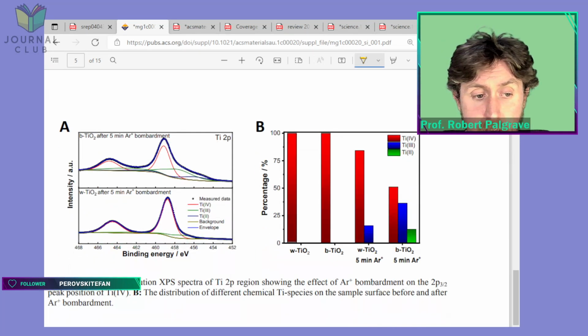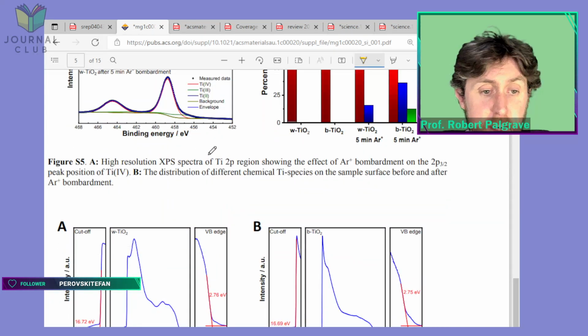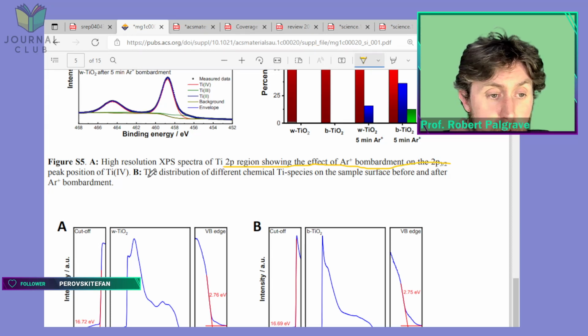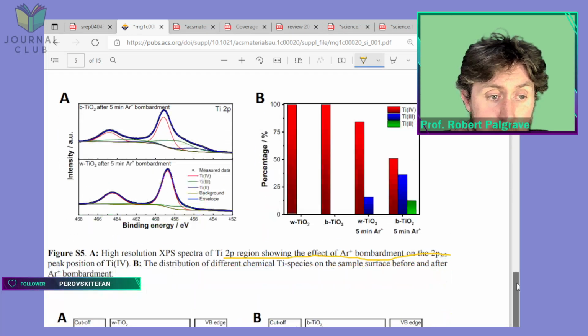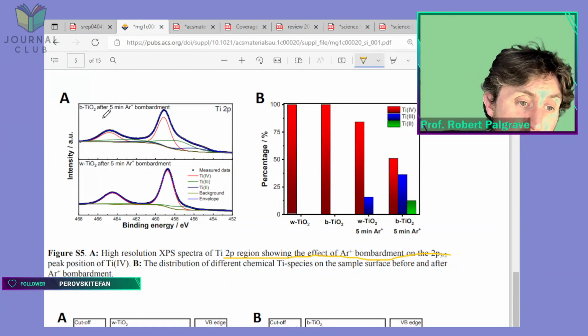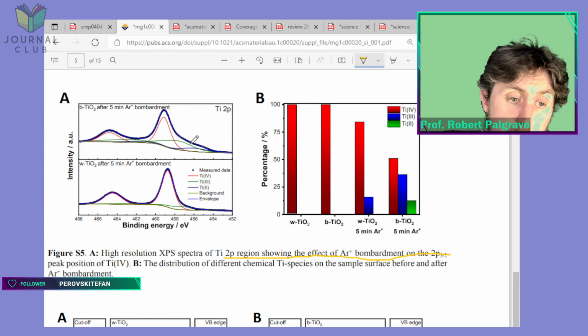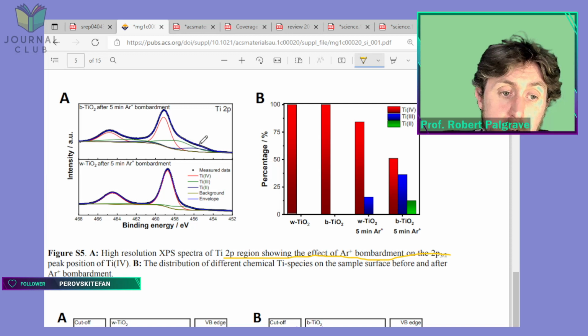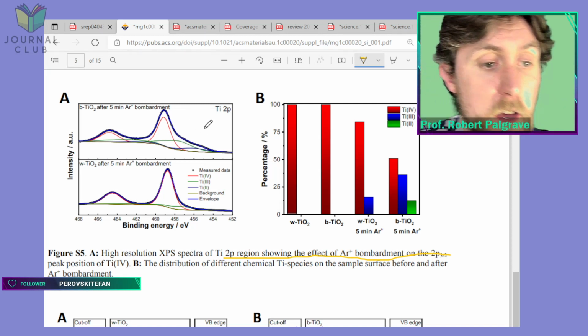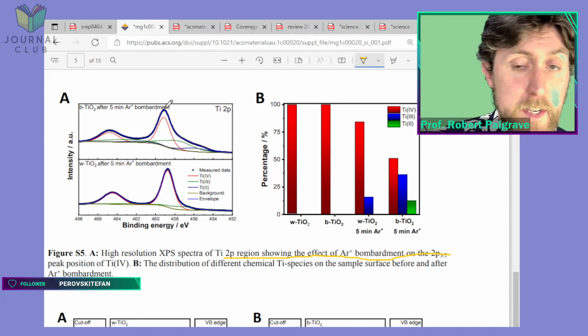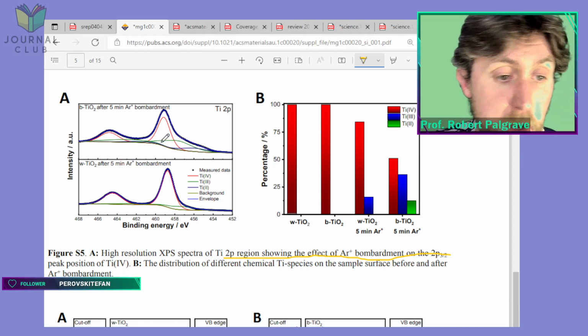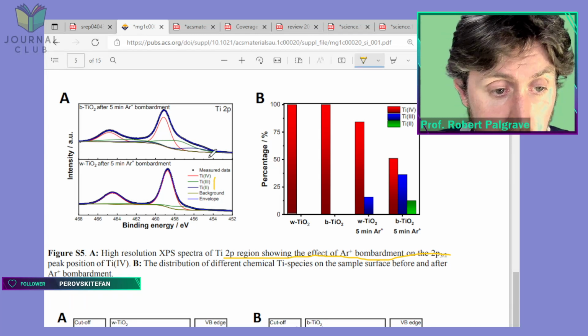As we can see here in the supporting information, high resolution XPS of the Ti2p region showing the effect of argon ion bombardment on the 2p3/2 peak position of titanium 4+. Let's look at the spectra first. Black TiO2 after 5 minutes argon ion bombardment. Interesting. You now suddenly get a lot of these extra low binding energy environments, which will be to do with the reduced forms of titanium. Titanium 3+ and titanium 2+ is what they're assigning them as. You can see them here. That may well be correct.